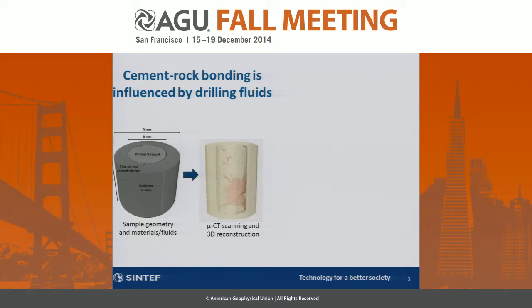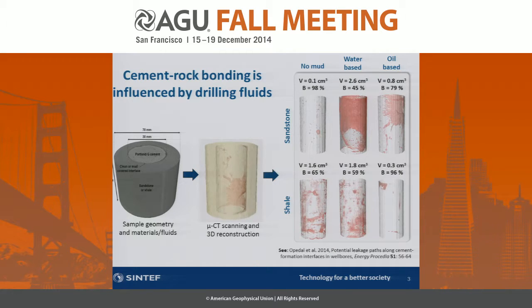And we identified the porosity at the interface between cement and rock. That's the pinkish stuff that you see in the volumes here. And we did that for a lot of samples. I'll show you 6 of them here. So we also had filter cake at the edge of the sandstone and the cement. In this case, you see the no mud, the water-based mud, and the oil-based mud cases.